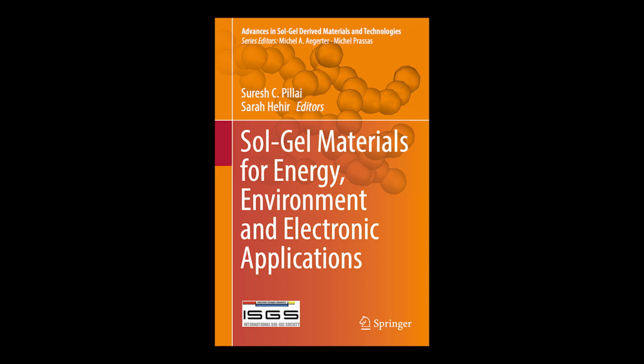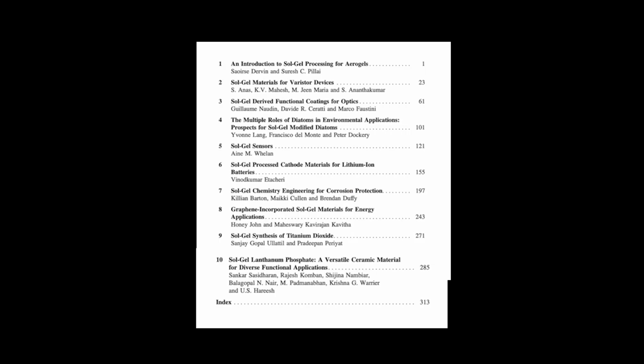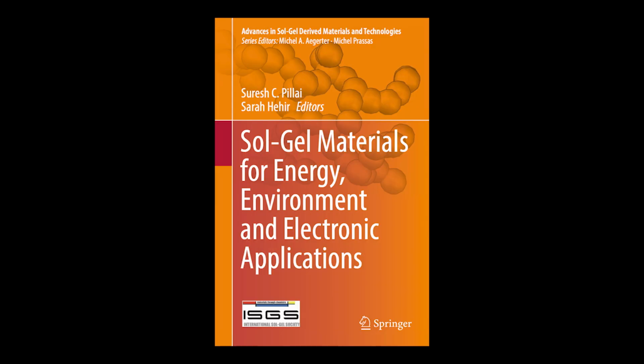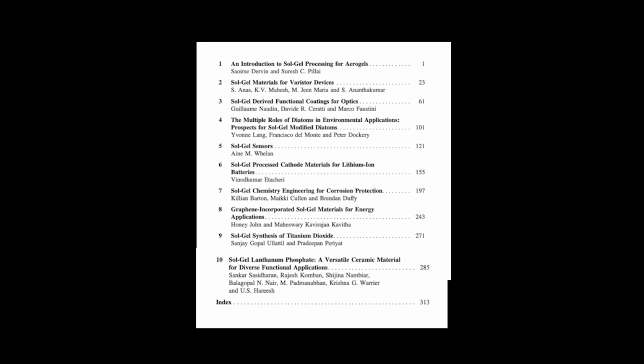You infiltrate the structure with a sol-gel precursor for, say, TiO2 or maybe zinc sulfide, and let it solidify. Then you carefully remove the original biosilica, often by dissolving it or burning it away at high temperature. What you're left with is a perfect structural replica of the diatom shell, but made of a different material, metal, semiconductor, whatever you chose. These replicas are being studied for applications in enhanced catalysis, light trapping in solar cells, and advanced energy storage because they inherit that amazing high surface area and intricate structure. And the other approach? The second and often simpler strategy is modification. This involves keeping the native biosilica frustule intact, but chemically altering its surface using sol-gel techniques or similar chemistry.